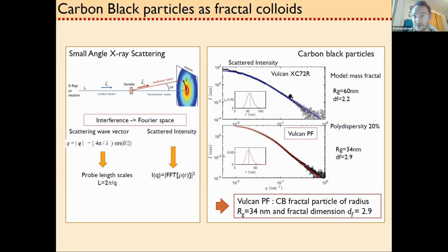So those are two different carbon black particles in the very dilute regime. So that's a form factor. And what you see is that basically it's flat here. So you have a cutoff here, which sets basically the size of your particle. And here you have a power law, which basically sets the fractal dimension of your particle.